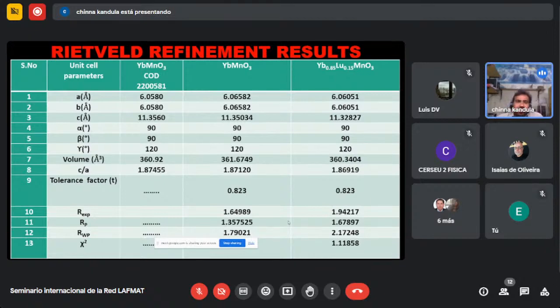The lattice constant value, if you see it, is reduced, and the overall volume also. The parent compound comes to around 361.6749 angstrom cubed, but with 15% lutetium dopant on the Yb site, it is reduced. This is because the ionic radius of lutetium is smaller than that of Yb. Because of that, the volume shrinks overall. That's why the entire unit cell volume of the lutetium-doped sample is reduced compared to the parent compound. So I calculated the tolerance factor.